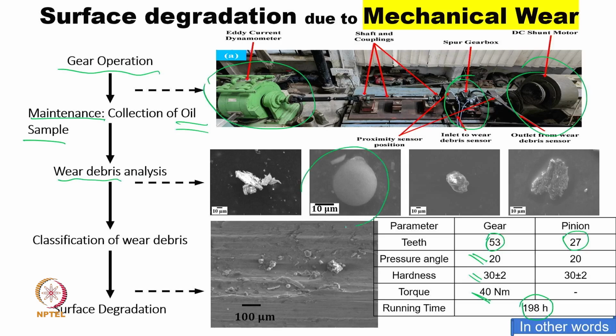You can see this is a 10 micron, the bigger particle. This is also a kind of plate formation with some sort of edge also. This is a very small particle size, and this is another flake, the bigger size dimension. So, these are important, we can use a SEM to look at the details of this. And at 100 micron I am able to show the surface also. So, it is interesting. You can see the debris which I get from the oil, and the surface also has this debris. So, debris does not come immediately out of the surface. When you try to analyze it, quite possibly some debris will remain stuck to the surface, maybe because of adhesion, because abrasion embedment happens, or maybe it is still in the process of wearing out, in the process of the damage. So, you can see here the surface degradation is related.